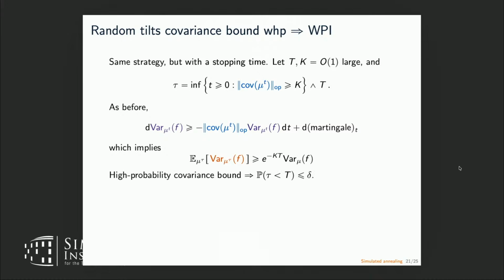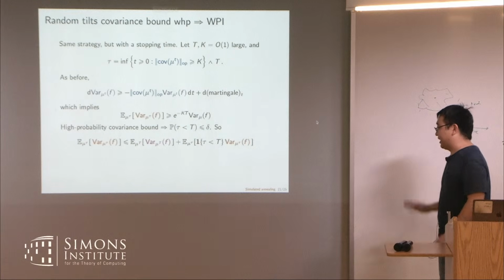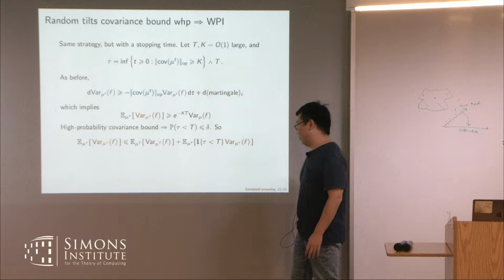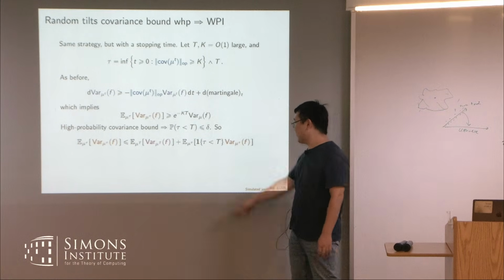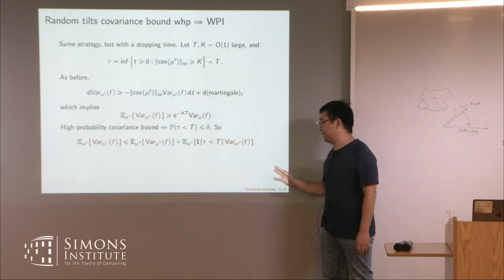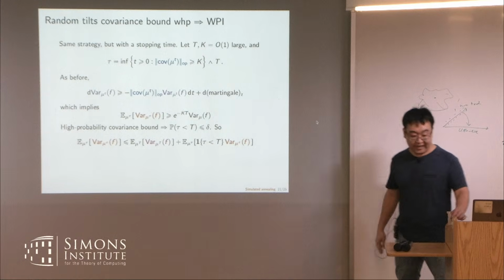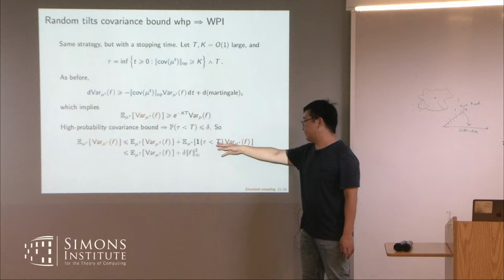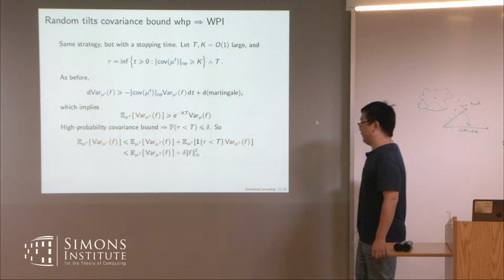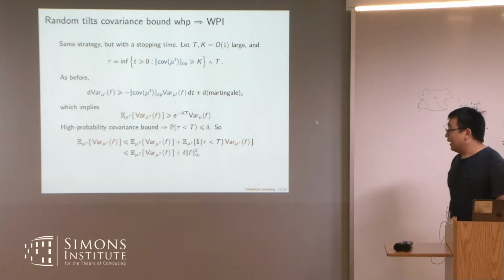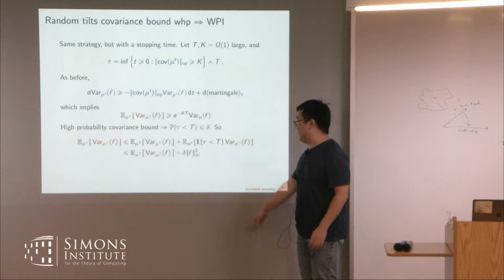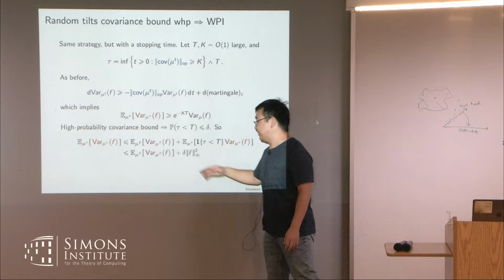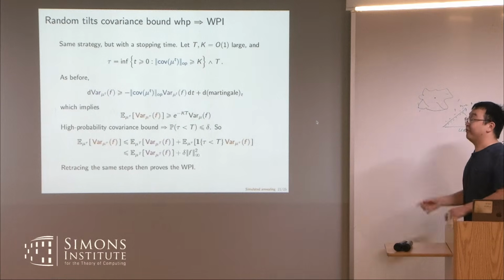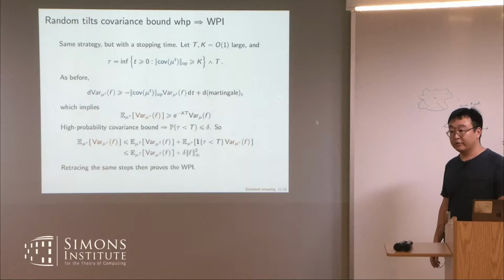This is where the high probability covariance bound enters. This bound exactly says that the probability that tau is not t is small. So then we can break up this time tau variance into the good term, which is time t, and the bad term, which is the contribution of the event that tau is not t. And we can bound this last term extremely crudely by just the probability of this event times the L infinity bound on the variance. So if you put this together, then you get to relate the time 0 variance to the time t variance and a small error. If you go around the rectangle again, then this will prove a weak Poincare inequality.